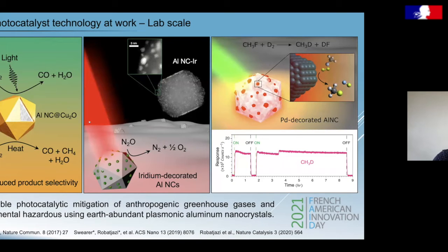We have used this approach in the past to demonstrate sustainable light-driven chemistry for several environmentally and industrially relevant reactions. Here are some examples of my PhD work. For example, using earth-abundant plasmonic aluminum nanocrystals as an antenna to capture light, and then coating these aluminum nanocrystals with a layer of copper oxides or decorating their surface with small, tiny islands of iridium or palladium. We showed that it's possible to use light to mitigate anthropogenic carbon dioxide through selective hydrogenation of carbon dioxide. And also we can dissociate nitrous oxide into synthetic air. And it turns out that we can also use light to break a strong carbon-fluorine bond in the fluoromethane molecule, which is the smallest member of the HFC family of compounds.